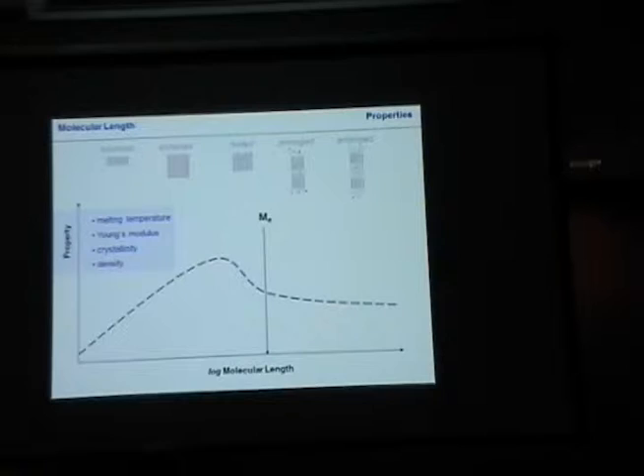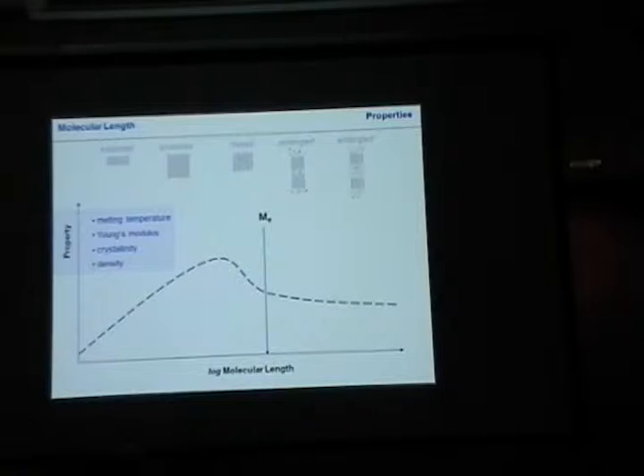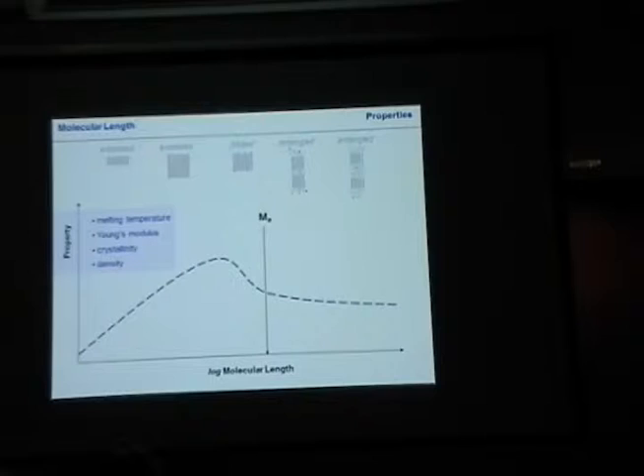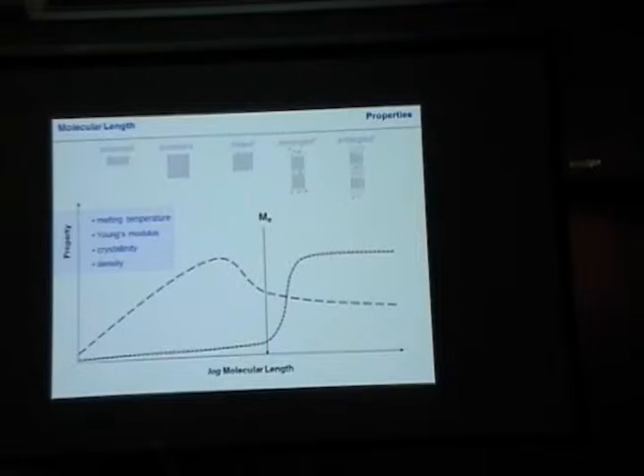We often use that in my lab to compare samples about lamellar crystal thickness. That's not the crystal size you measure in X-ray — what you measure from the peak width in X-ray is actually the XY dimension. What is relevant for the melting temperature is really the Z direction. This is also relevant for electronics because crystallinity, which we often correlate with charge transport properties, exactly follows this trend too.